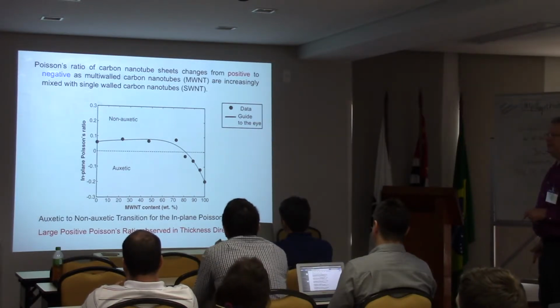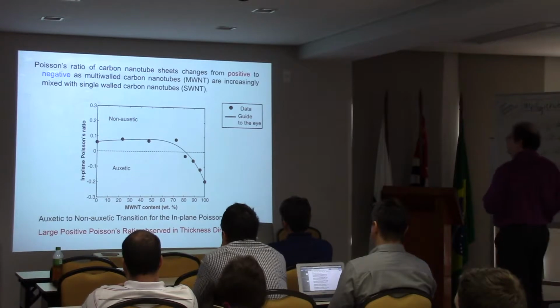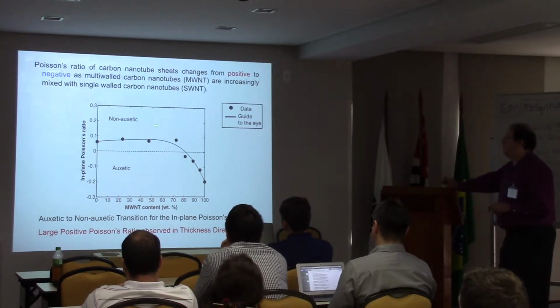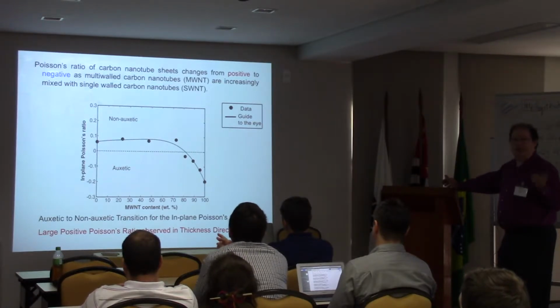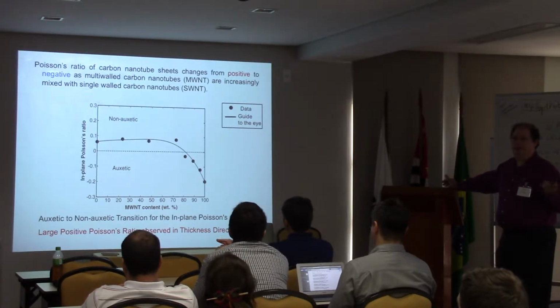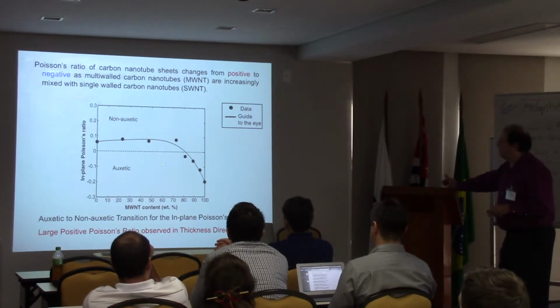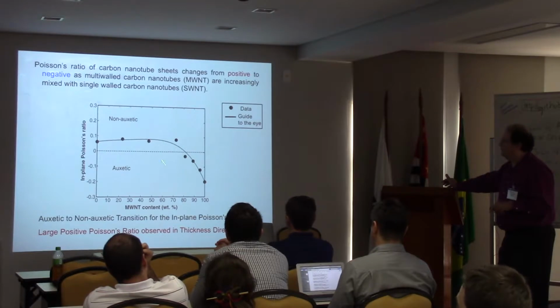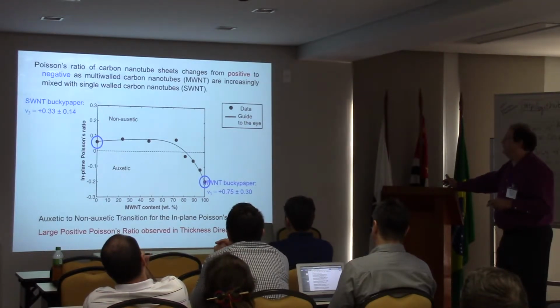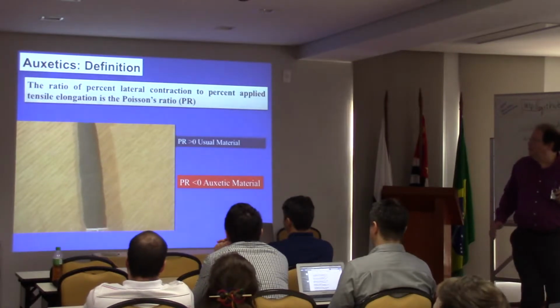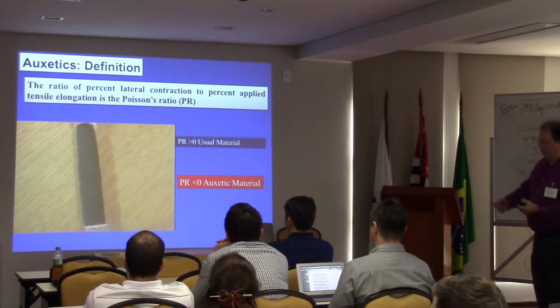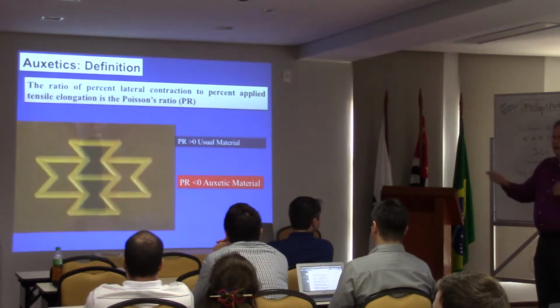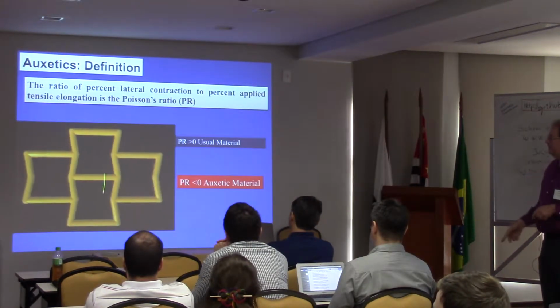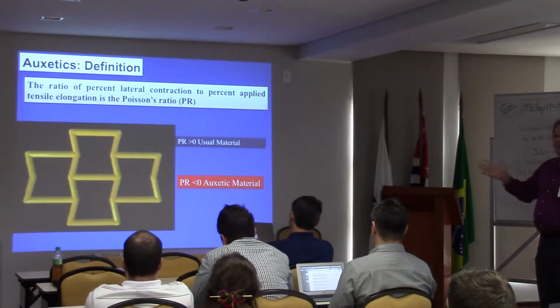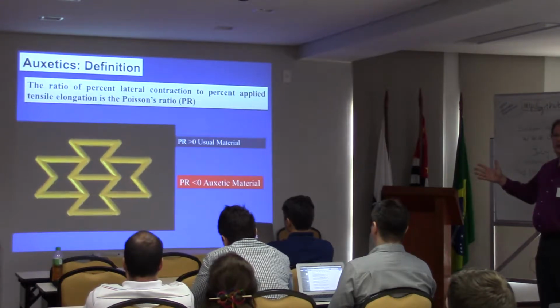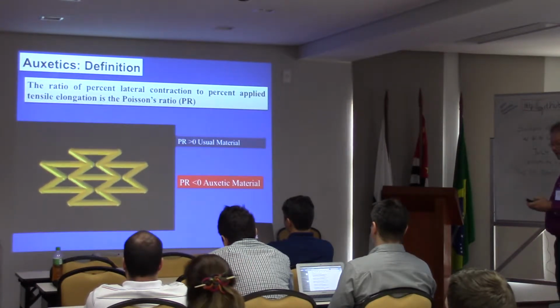When they did this for the first time, they had very interesting results. They observed for the first time a transition from auxetic to non-auxetic materials and back, from non-auxetic to auxetic, just by changing the content of the mixing. Okay? If you do not remember, auxetic materials are quite simple. In general, when you stretch a material, it becomes thinner along the direction you're stretching. This class of material has a counterintuitive behavior. When you stretch, it expands perpendicular to the direction where you're stretching it. There are very few materials in nature that can do this.